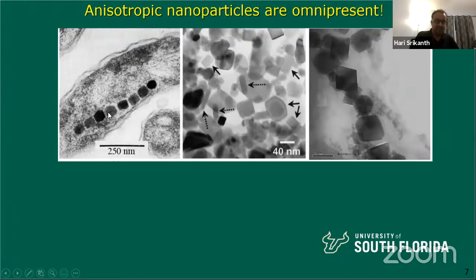Now it turns out that these are actually magnetotactic bacteria. These are organisms that actually produce magnetite nanocrystals. You can see the scale bar here. That's 250 nanometers. So these are beautiful 20 nanometer particles, and they're chained up here. They're chained up to form these short chains using dipolar coupling.